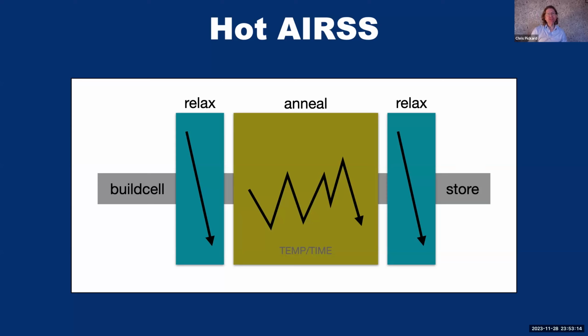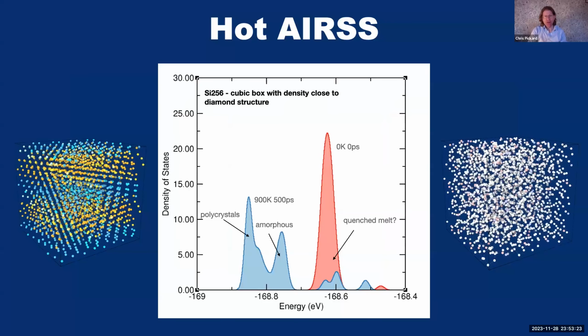But the difference is in the quantity. Now we're doing maybe thousands or tens of thousands of molecular dynamics simulations all at once. And the powerful thing that allows us to do is we can now do structural searches using thousands and thousands of molecular dynamics simulations, and you see a very different picture. So what I'm showing here is a structure search done with 256 silicon atoms in a cubic periodic unit cell with the density close to the diamond structure.